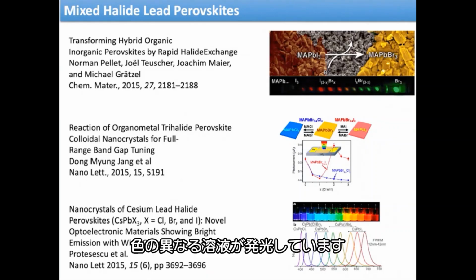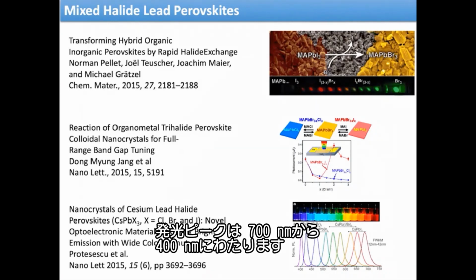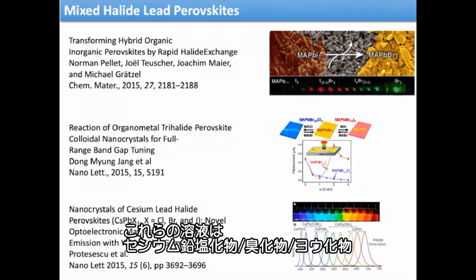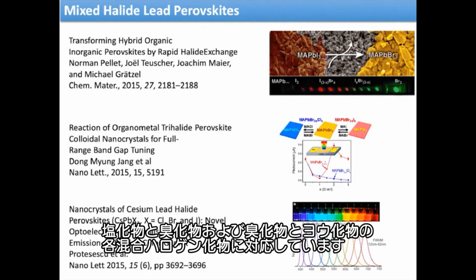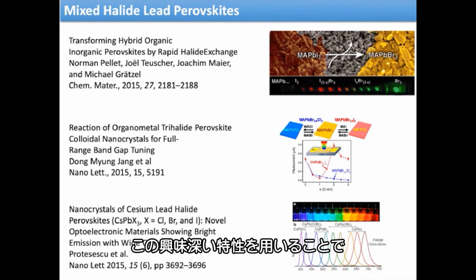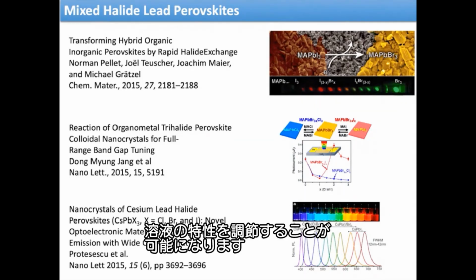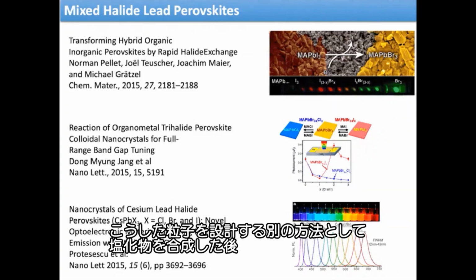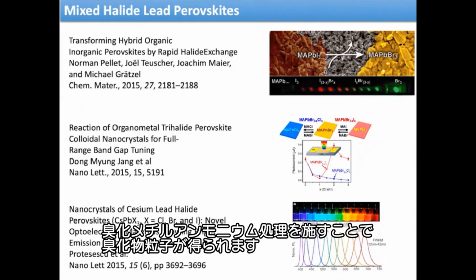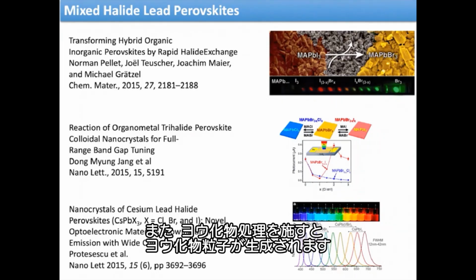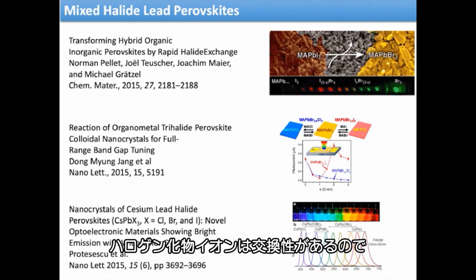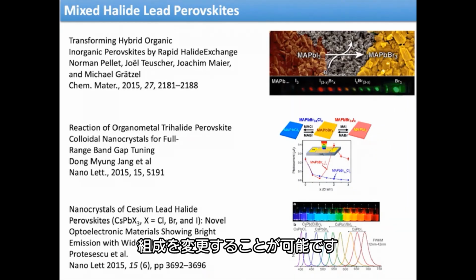And in the bottom of this slide you see different colored solutions emitting light, and they range from 700 nanometer peak emission to 400 nanometer peak emission, and these correspond to the cesium lead chloride, bromide and iodide, along with mixed halide containing both chloride and bromide, or bromide and iodide. So this is a very interesting property that one can use to tune these properties. Another way to design these particles is you make one class of, say, chloride, and then treat with methylammonium bromide, and you get bromide particles, or treat with iodide, you make iodide particles. So these exchangeable halide ions allow you to get different compositions.